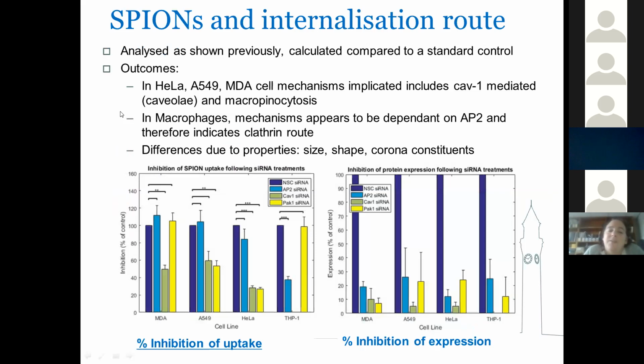So what we found was that the HeLa and the A549 and MDA cells all included a CAV1 mediated uptake and a macropinocytosis. So the particles were able to go in through more than one mechanism. And this is really important because it means that if one mechanism is shut down or is poisoned, the particles were still going in, but by an alternative method. So they could use multiple uptake pathways.